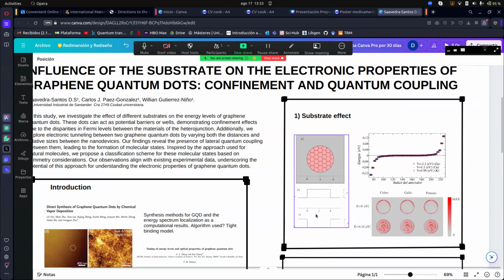The energy spectrum reveals that change in substrate doesn't significantly affect the energy levels, indicating no evident change in energy. Similarly, the densities of states presented below don't reflect a change in the localization of the electron. At energy close to the Fermi level, where the degeneracy of this energy value is shown, the electron is localized at the edge of the quantum dot. However, as the energy increases, the electron begins to localize within the quantum dot. Two bands of higher intensity emerge, which reflect the movement of the wave function and its interference at the Dirac K points, as the figure shows.